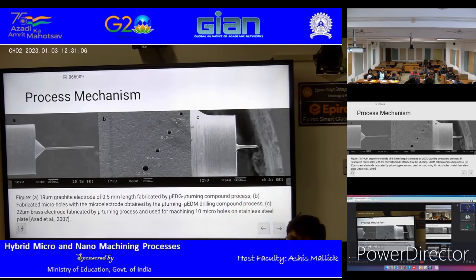Now, there is another process in microEDM we call self-drilled hole. The hole that you machine also causes some electrode wear, which reduces the tool electrode. So if you machine multiple times, your tool is getting shorter also, and that will help you achieve smaller holes. I remember Asad et al., he's one of the co-authors in some of my papers, and I think this micro turning, especially this one, was his work, but we have several papers and we worked on those together. After some time, you just stop making electrodes and just machine several times, so that you can get smaller holes. This has been patented also as the smallest hole using the microEDM process.